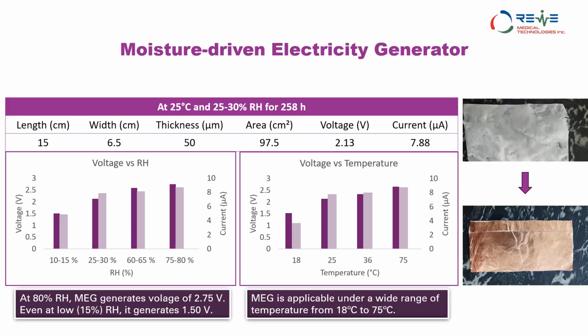Using the humidity responsive hydrogels, we have developed this moisture driven electricity generator. It was developed using a very simple method of solvent casting, and its thickness is 50 microns. The voltage that it generates is 2.13 volts, and it generates 7.88 microamperes of current. It can be seen here that at 25 to 30% relative humidity, it is generating a voltage of 2.13 volts, which increases with increasing relative humidity. Similarly, if we look at the relation with temperature, increasing the temperature increases the voltage.